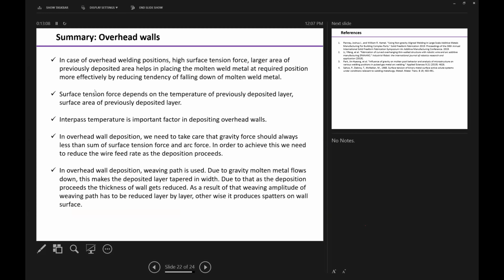So the summary of this preliminary investigation is that in the case of the overhead position, high surface tension force and a larger area of the previously deposited layer help in placing the molten metal at the required position. The surface tension depends upon the temperature of the previously deposited layer, so the interpass temperature is an important factor in depositing overhead walls. In overhead wall deposition, we need to take care that the gravity force is always less than the sum of the surface tension force and the arc force. To achieve that, we need to reduce the wire feed rate as the deposition proceeds. So the main controlling factors in this deposition are the wire feed rate, travel speed, and the interpass temperature. If we control these 3 parameters, then we will be able to deposit a wall of good quality.